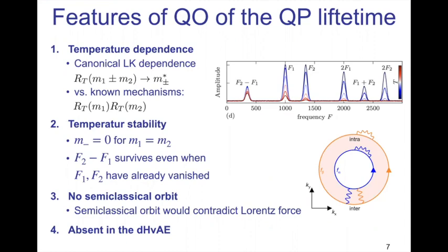But when you increase temperature, your main frequencies will go down. However, your difference frequency can remain finite. And even though it's only a modulation of the main frequencies, it can become the dominant part of your spectrum.